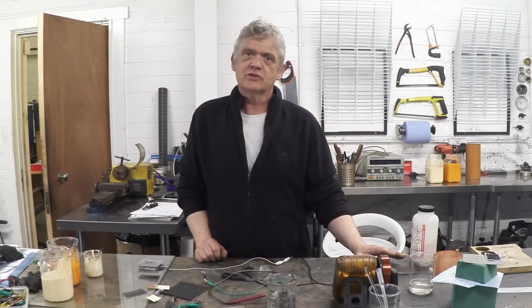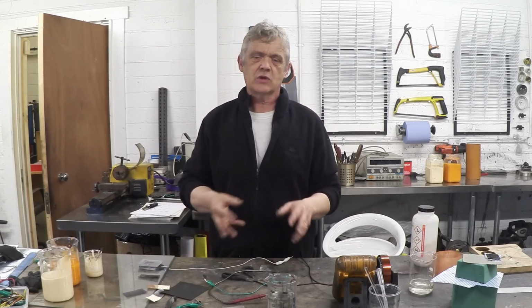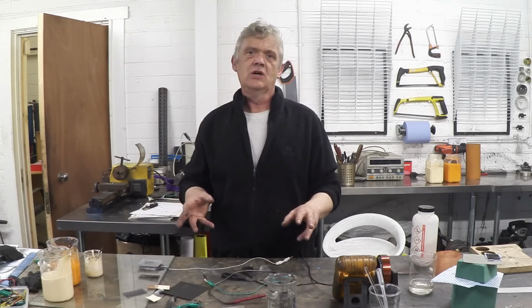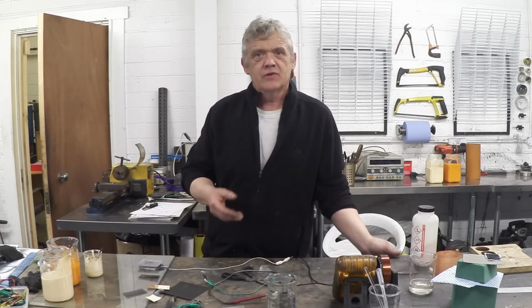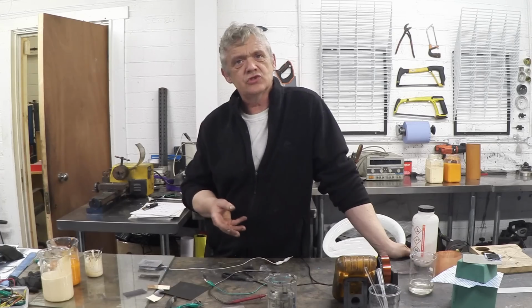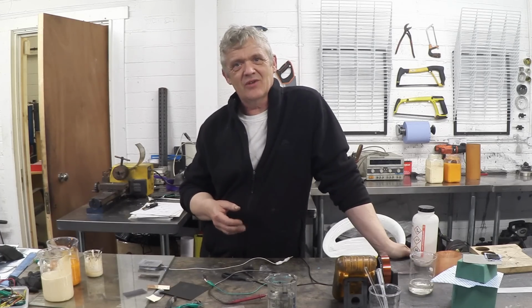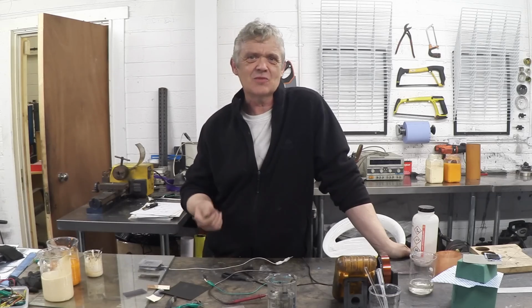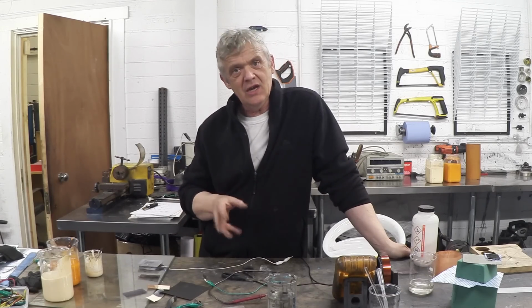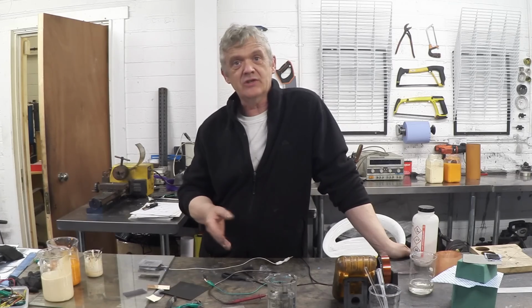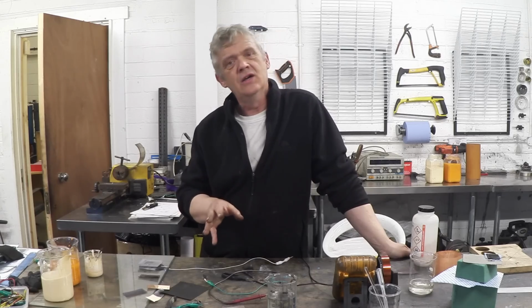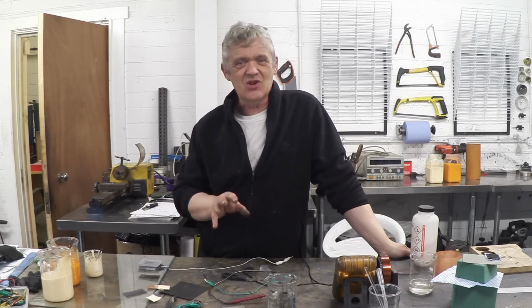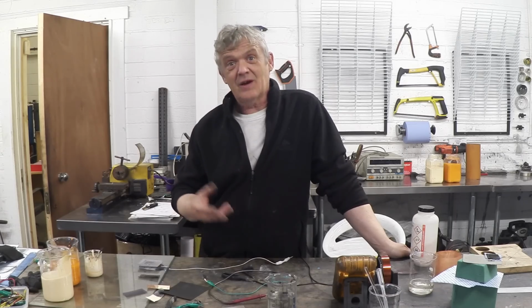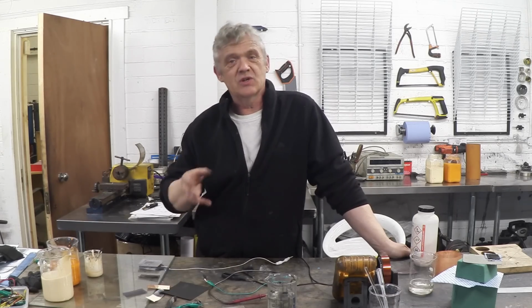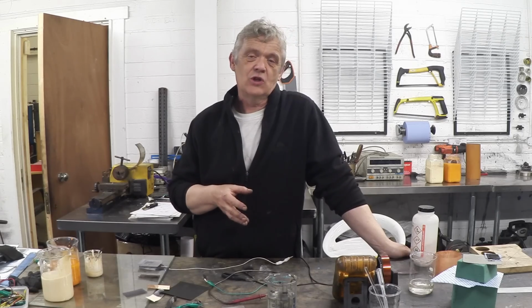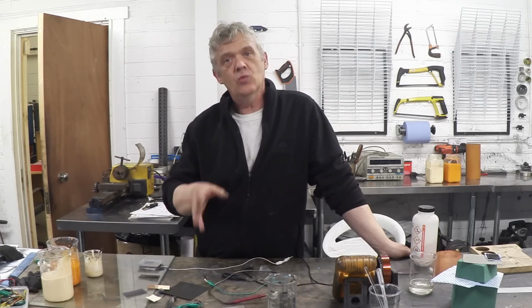These copper oxide solar cells in themselves are fun to make and they're great to explore the science, but they don't put an awful lot of power out. But they are the basis, I think, for developing our own solar cells. Now, we need to take more care rather than just chucking a plate on top of a hob and hoping it's going to cook properly. But not that much more care. Like I say, in air, in an oven, 230 degrees, 30 minutes, or 400 degrees, which is better if you can get there, for about 5 or 10 minutes will form you the right kind of coating that you're looking for. Then we can modify that, play with it, and make better solar cells that we can actually use. Real solar cells that will approach the power of current solar cells that we can make ourselves.